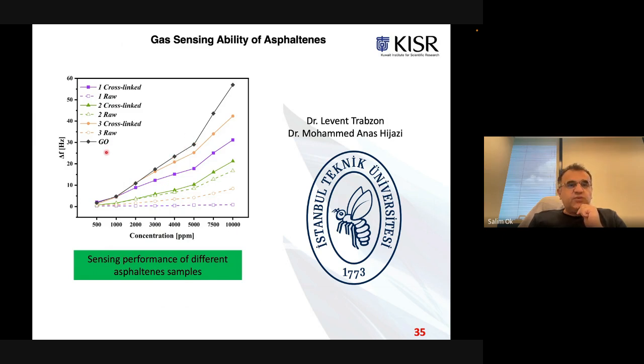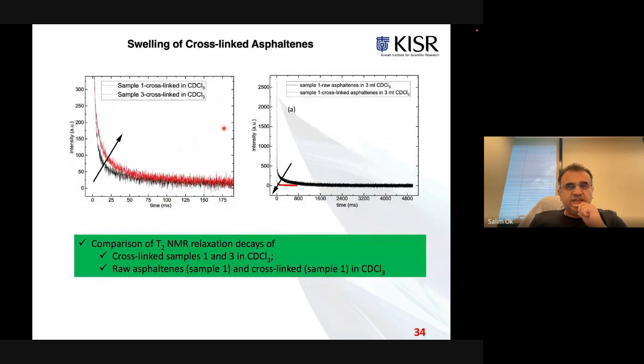When we switch from raw asphaltenes to cross-linked asphaltenes, the gas sensing performance of different asphaltene samples increases. So switching from raw to cross-linked, or modified, asphaltenes gave a pretty nice result. The gas sensing ability of asphaltenes, especially for certain molecules such as ethanol and isopropanol, was shown pretty successfully.